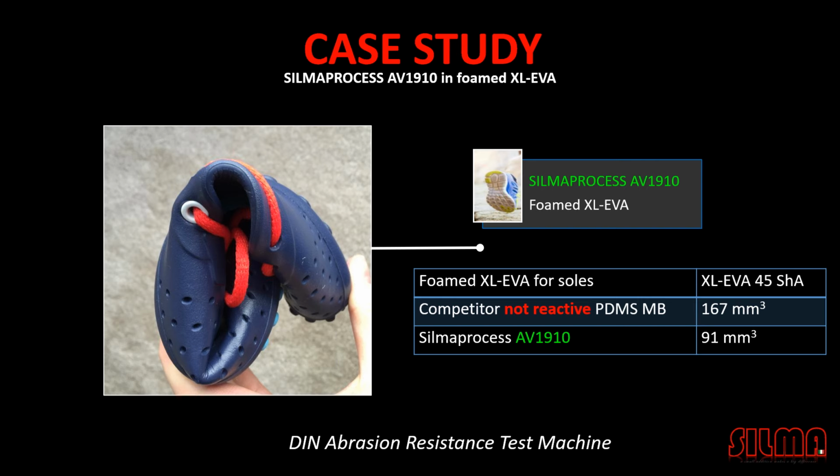This is a big slide mentioning more or less a summary of the surface properties that we want to be permanent. The starting point is that the highly migrating, low molecular weight, basic polydimethylsiloxane, commonly called silicone oil, gives, of course, benefit. But abrasion resistance is only temporary, just after the injection and just after a few times. And SILMA studied deeply how to make the migration permanent, the surface performances of modified rubber. And there are different technologies depending on the polymers.